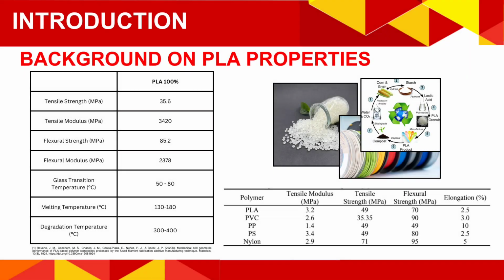Before diving into our research, it's important to understand the baseline properties of PLA or polylactic acid, which serves as the main polymer in our study. PLA is widely used in biomedical and 3D printing applications due to its biodegradability and good mechanical properties. As shown in the table, pure PLA has a tensile strength of 35.6 megapascal, a tensile modulus of 3,420 megapascal, and a flexural strength of 85.2 megapascal, indicating its rigidity and strength. Its glass transition and melting temperatures range from 50 to 180 degrees Celsius, making it suitable for thermal processing.